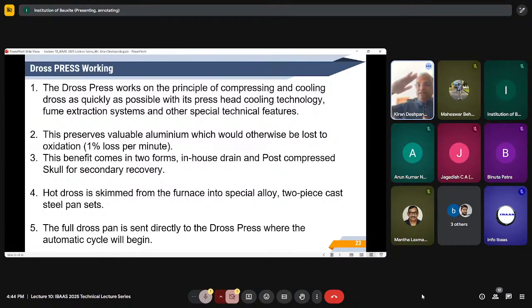Pressing cycle, meaning door opening and closing cycle, is 6 minutes. Within 6 minutes, you can press the DROSS. Now the DROSS pan capacities are 50 kg to 3 tons. So we have 3 ton DROSS pans. You skim the DROSS, put it into the pan. The pan should be 80% filled. Take that pan into the press and press it. And we can tell you that the recovered aluminum is 25% of the weight of the DROSS. Okay, next slide.